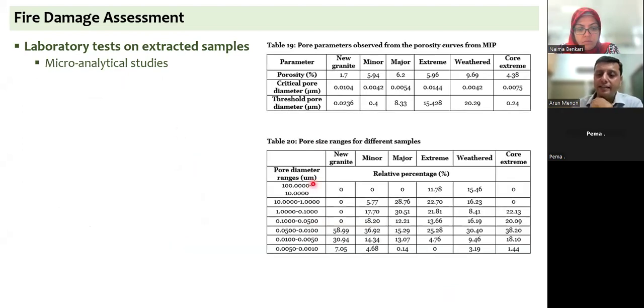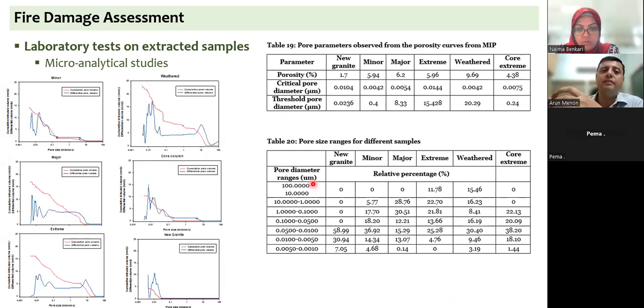The microanalytical studies were very interesting. We were able to see how the fire had affected the stone, using this particular test called mercury intrusion porosimetry, in which mercury is, under pressure, filled into the pores of a sample of granite. And you take measurements of how much mercury is being used up. Those measurements can give you an idea of the pore size distribution and the sizes of pores. And it was very interesting to see how the fire had actually affected the outer layers of the stone quite significantly, whereas the inner layers of the stone were more or less conserved.